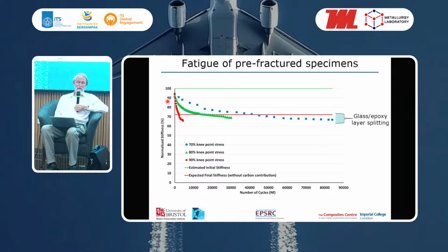So overall, I think that's quite a good response, because these materials, we would not want to operate them above the knee point strain. So the design strains would be below that knee point, and so occasionally, if you've got an overload event, which is one of the things that we would want these materials for, to be able to cope with that overload event, you can overload it and still cycle it at quite high stress levels and not see an immediate delamination. So I think that shows that these materials are quite good from fatigue, and that's a very positive aspect.